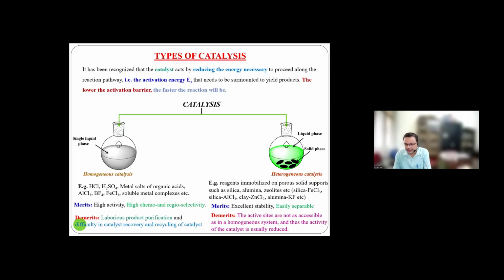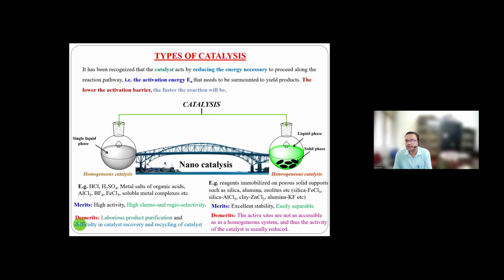To get rid of this problem, scientists developed nanocatalysts. They bridge the gap between homogeneous and heterogeneous catalysts. Nanoparticles are in the range of 1 to 100 nanometers. They have a large surface-to-volume ratio, so their reactivity is very high compared to the homogeneous catalyst, and they can also be separated by easy techniques like centrifugation and filtration.